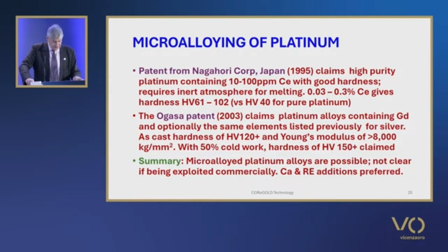A platinum cerium phase diagram shows characteristics similar to that of the gold cerium system. For cerium contents of 0.03 to 0.3%, hardness values of 60 to 102 were obtained compared to 40 Vickers for pure platinum, and hardnesses of 120 to 136 for 950 fineness platinum alloys. A commercial alloy, UHP platinum from Japan, appears to be a microalloyed platinum at 999.5 fineness, but little information is available.